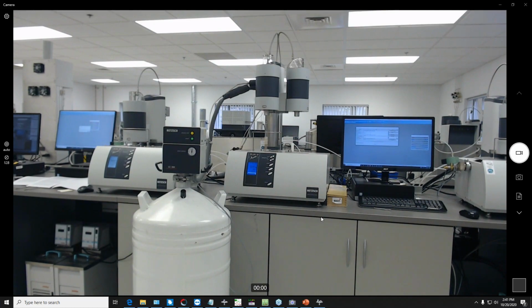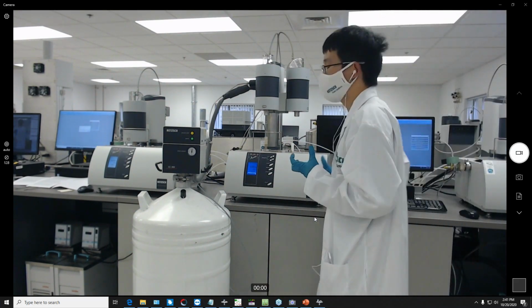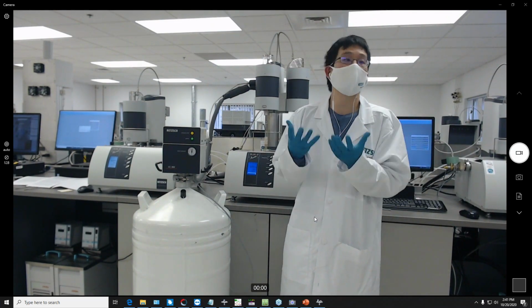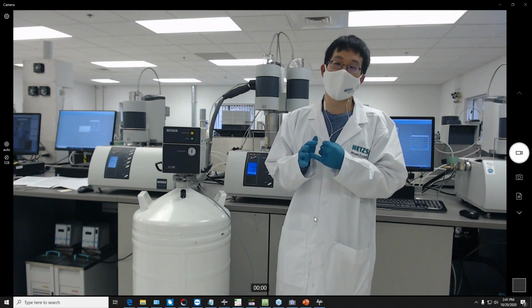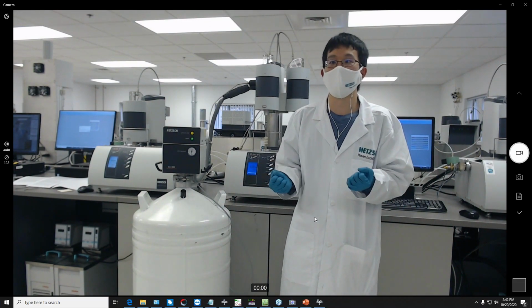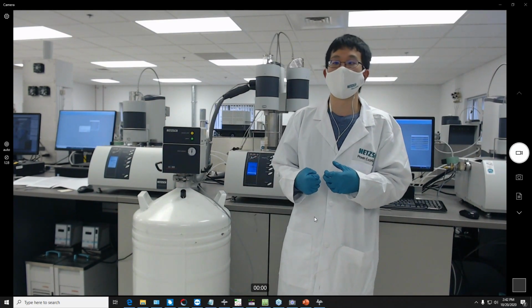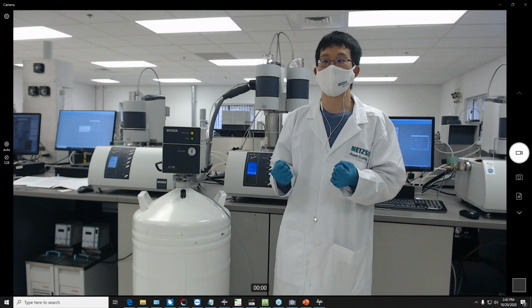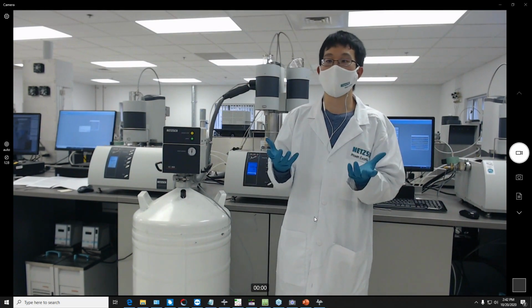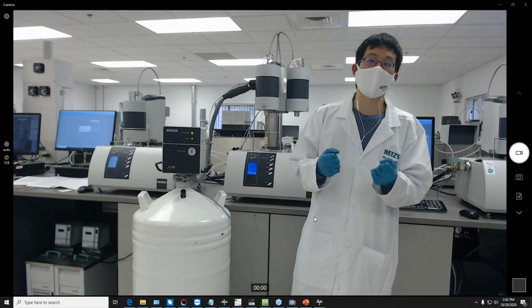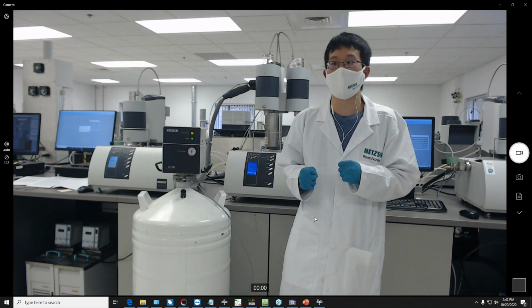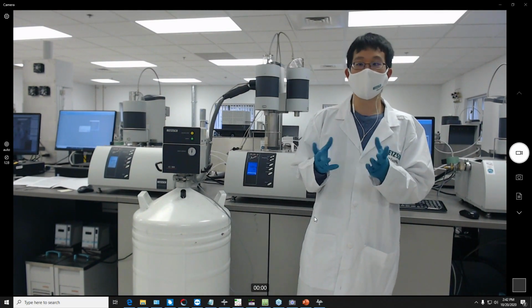For the high heating rate furnace, are pyrolysis experiments for fossil fuels okay, or could they damage the furnace? And are the recommended gas flows similar to the ones used in the water vapor furnace? Usually what I recommend when users ask me questions about sample measurements is that first you want to have an idea of what could happen. With fossil fuels, if you're heating in, let's say, an oxidative environment, you might have a lot of exothermic reaction and heat. In those situations, there could be some potential for damage to either the sensor or the equipment itself if it releases a lot, sort of like an explosion. So you want to be careful.